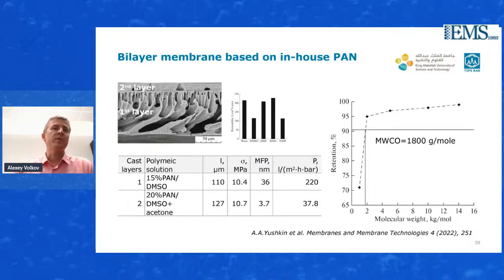So we took the first layer made of the PAN, and for that case, we used 15% of the PAN solution in DMSO. On the central small graph, there are fluxes, that is, the permeance of the different solvents or aprotic solvents through the treated porous support. And then we cast the selective layer made of another composition of the same polymer, but that's 20% of the PAN in DMSO plus acetone.